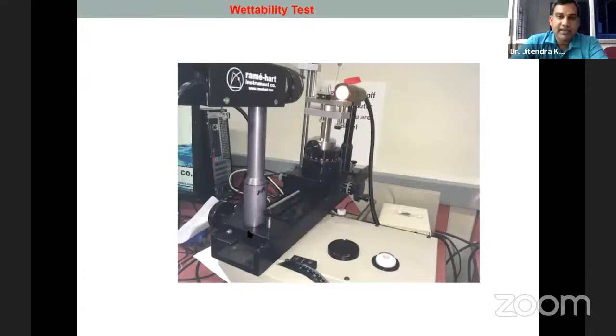So next, if you perform the coating, then we check whether the coating surface is hydrophobic or hydrophilic in nature. So this is the goniometer which you use here. This is a manual goniometer. Here you can move it by this wheel according to this tray. And here you just keep your sample, and from the top you drop your water droplet. That is 2 microliter.